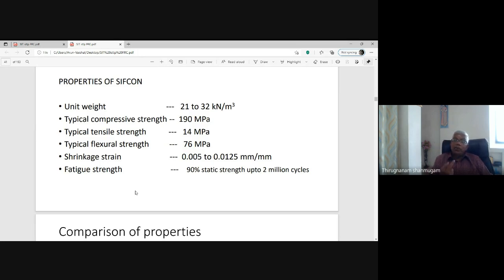The typical tensile strength is 1 Newton per mm square for M20 concrete, but here the tensile strength is about 14 Newton per mm square, greater than 10 times. The flexural strength, FCR, is 4 Newton per mm square for M20 concrete. But for SIFCON, the typical flexural strength is 76 or 80 Newton per mm square, 20 times more than that. So the contribution of fiber is significantly seen in flexural strength. A large amount of flexural tensile strength is there. Shrinkage is very, very low, and the fatigue strength is very high, 90% of static strength up to 2 million cycles.